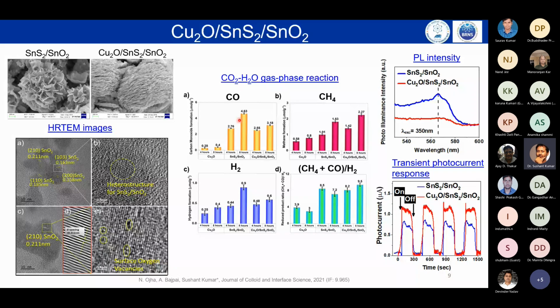We performed some more characterizations. Starting with the PL intensity, we saw that yes, Cu2O again helps in prohibiting the recombination events. Then when we look at the transient photocurrent response, which tells about the electron mobility, as expected, this photocatalyst showed a better photocurrent when we switched the light on and off, as compared to SnS2. When the light was off, you can see that there was no current, and once again when the light was on, there was a consistent performance in the Cu2O, SnS2, and SnO2.